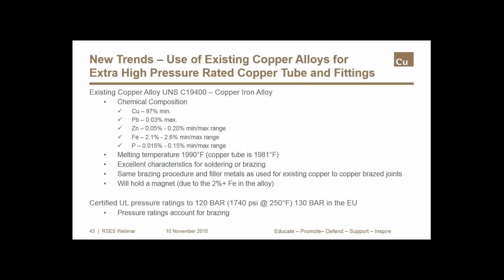So let's turn our attention now to a copper alloy, alloy C194, that's now being used to produce tube for extra high pressure applications. If we look at the composition, that 2 to 2.5% of iron in this alloy is really what gives it the strength to handle working pressures of over 1700 psi. And that pressure rating is UL certified.